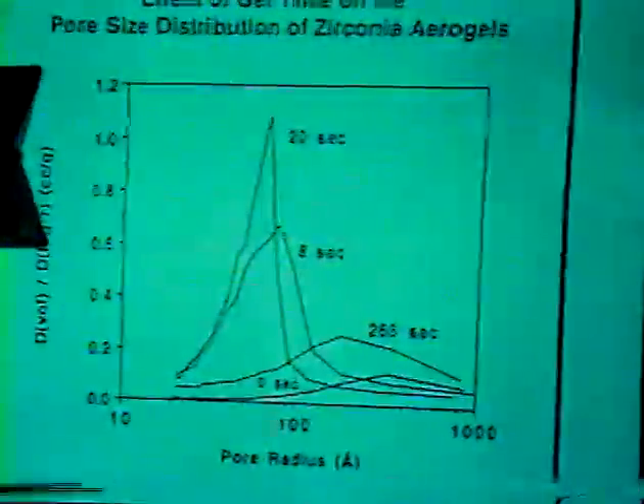Not surprisingly, the corresponding pore size distribution also shows this effect. What we are looking at now is the pore size distribution for the various gel times that I showed you earlier. The bottom curve, a gel time of 0 seconds, corresponds to actually a precipitated sample. In other words, the gel did not even form. As you go to very long gel time, in this case about 270 seconds, again you have a very broad distribution. Only by controlling the acid and water ratio to obtain a gel time of around 8 to 20 seconds,